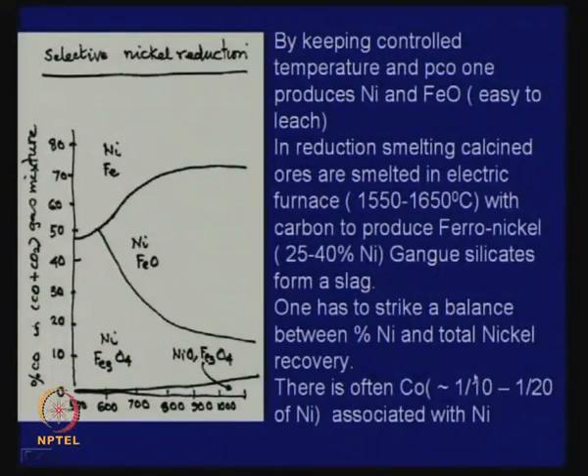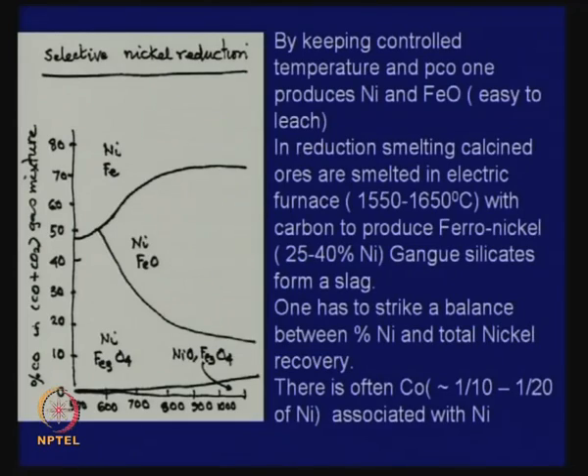Now, in pyrometallurgy we go a bit differently. We combine the initial reduction of the lateritic ores to such an extent that we produce nickel and FeO, Fe3O4, and that nickel can go for ammoniacal leaching. So, that charge which has been reduced under controlled atmosphere, in a rotating hearth furnace or a rotary kiln, can now be sent for ammonia leaching. Nickel can be easily leached by ammonia to produce nickel ammine, from which we can precipitate nickel carbonate, and nickel carbonate has an easy market, because if it is added anywhere, it will easily decompose and produce metallic nickel. So, from these oxidic ores one can produce ferronickel, and one can produce metallic nickel.